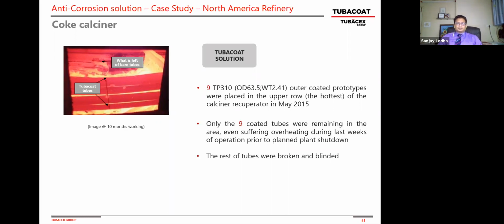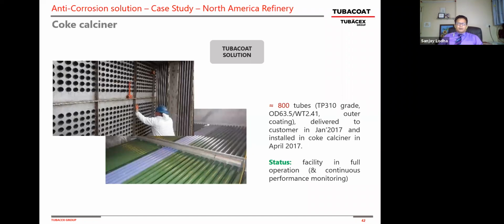So the light did so much that they decided to go for a full commercial trial, full commercial run, which I will show you in the next slide. So they went with 800 tubes, TP310, and as you can see, the 2 different color schemes of the TubaCoat technology. It's not just because we like different colors. They were designed for different temperatures. As I said, we designed these tubes and customized these tubes coatings for different applications, different conditions, different temperatures. So some of the tubes you see were designed for 700 to 750 degrees Celsius and some for another 20 degrees higher temperature. And they were installed in April 2017.